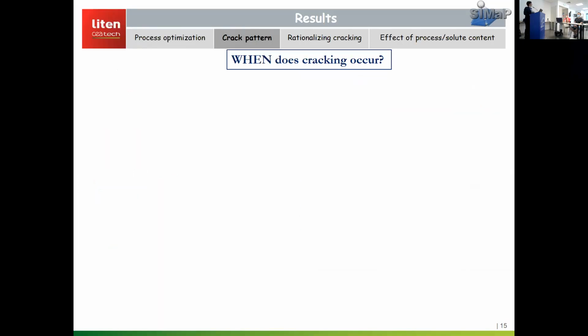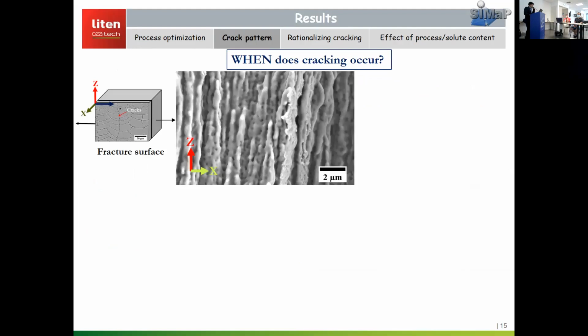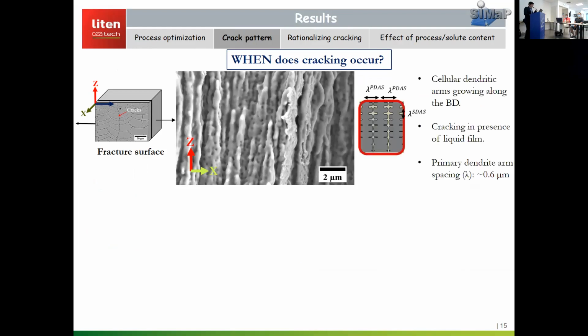Now let's see when cracking occurs. To do that, we did fracture surface analysis. We did a tensile experiment on the cubes perpendicular to the building direction. The aim was just to identify the fracture morphology. With the fracture morphology, we can understand the origin of cracking. For example, here you see cellular dendritic arms growing, and we see a bit of initiation of secondary dendrite arms, but those are still in their initiation phase.